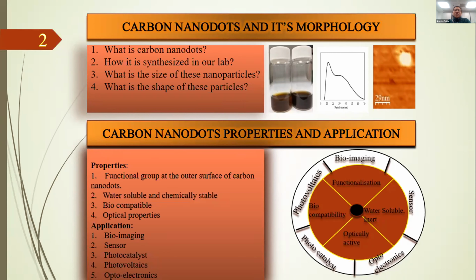It can act as a photocatalyst, as size-controlled carbon nanodots have a tunable emission from near IR to blue wavelength. So it can act as a promising candidate for photocatalysis. The strong fluorescence can sometimes be quenched in the presence of some metal ions, so it acts as a sensor for those particular metal ions.